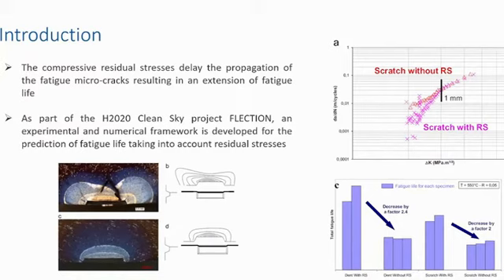This is proven even in the literature, where there are studies and it's known that residual stresses improve the fatigue life. In fact, here on the top right we can see the fatigue crack propagation rate of a scratch when there are residual stresses and when the residual stresses have been released. We can see that the crack progression rate when there are residual stresses is way lower, and this results in an increase in fatigue life of over 2 times. So the Clean Sky project I'm working on wants to develop an experimental and numerical framework for the prediction of the fatigue life, taking into account the damage and the residual stresses.